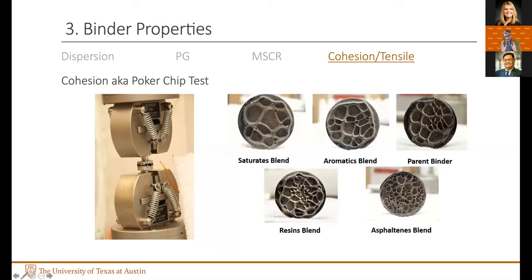Also keeping in mind that the asphalt binder in an asphalt mix never exists like a thick blob that you see in a DSR specimen. It's always confined, and the properties of an adhesive that is confined are very different from properties of an adhesive that is unconfined or in the bulk. You cannot take a tank of glue in the bulk and expect it to have the same properties when you confine it in a thin film. It's a very, very different behavior.